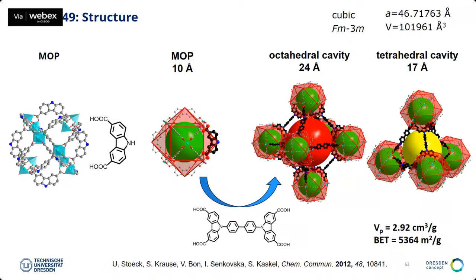But before I close, I also wanted to tell you about a different story, which was maybe a combination of serendipity and rational design. And this was a structure that we discovered in 2012. We call this material DUT-49. At that time, it was a very highly porous material, 5,300 square meters per gram. It's even higher than the material from Omar Yaghi. And this is also a very neat architecture. It's a very simple architecture in a sense.